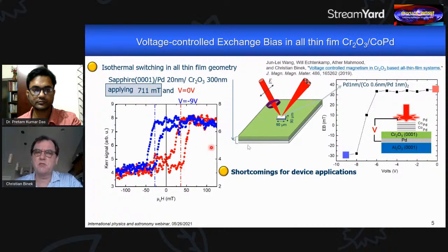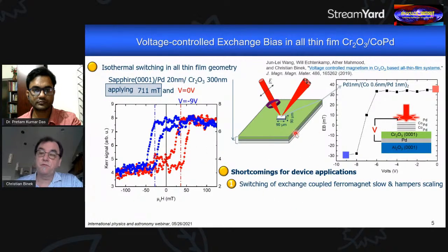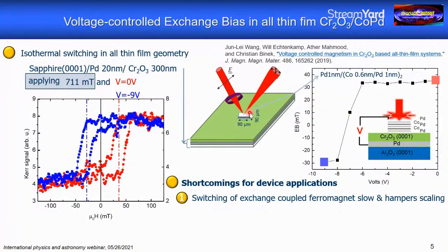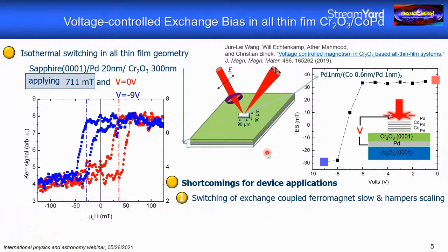So what are those shortcomings despite this success? Well, one is simply the fact that you have a ferromagnet on top. And for those of you who work in the field of spintronics, you know this is where all the excitement about antiferromagnetic spintronics comes from, namely simply the fact that antiferromagnets can be switched much faster than ferromagnets. The reason for that is that the switching of a ferromagnet is tied to the Larmor precession frequency which the ferromagnet has in the presence of the applied magnetic field. And that frequency is small, giving rise to switching speeds on a nanosecond time scale, and that is too slow.